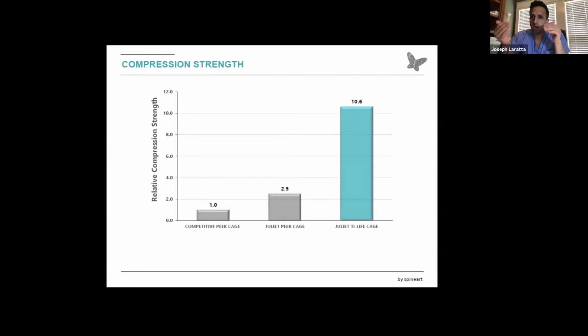The things that we really also need to realize is that modulus is not everything, right? So some of the failures of the porous implants that we've seen in the literature, some of the early tritanium cages, the tantalum cages. So tantalum cages were used in ACDFs and a couple of trials for anterior cervical fusion. And what happened with those was because they didn't provide enough compressive strength, there was an increased risk of catastrophic failure. So at the same time as we want to have the optimum modulus, we need to make sure that there is enough compressive strength to prevent catastrophic failure.